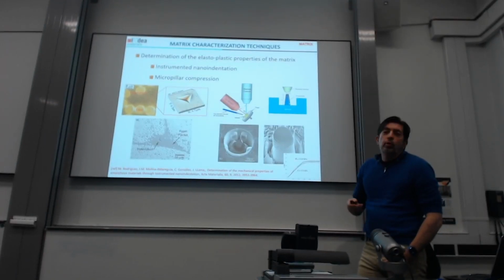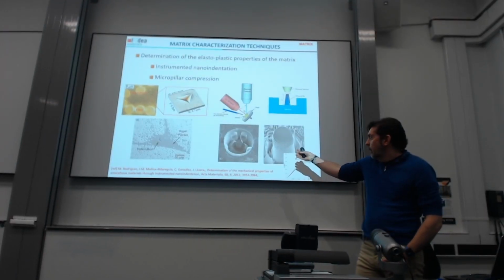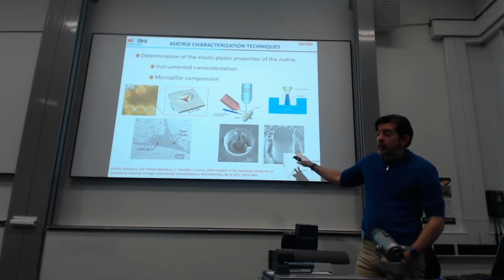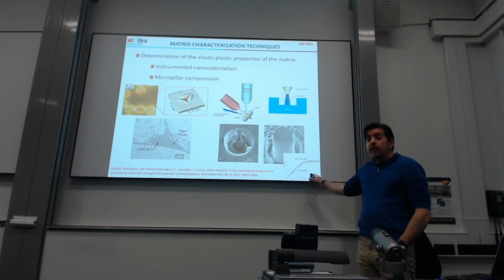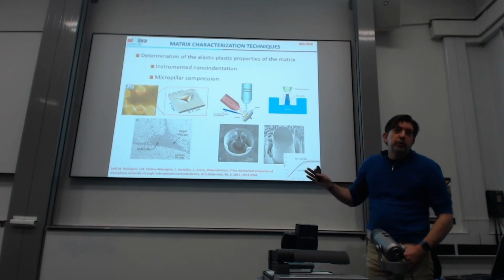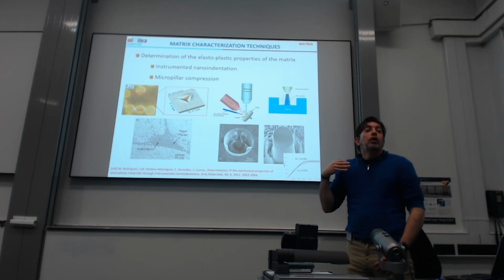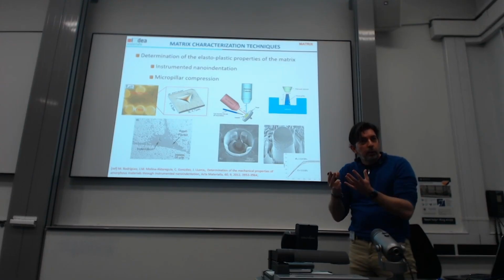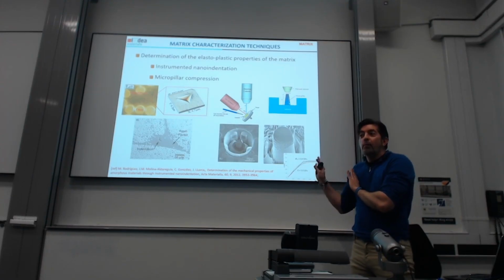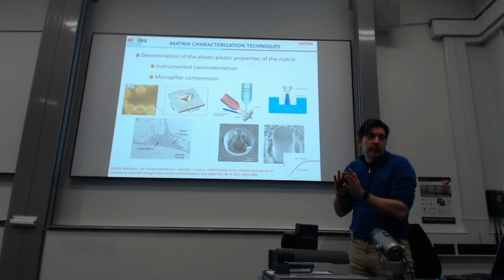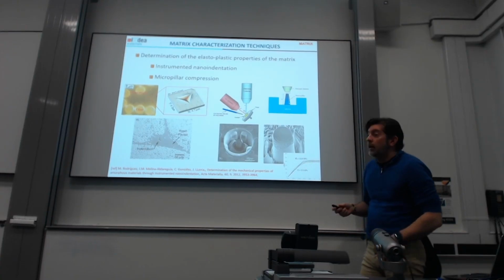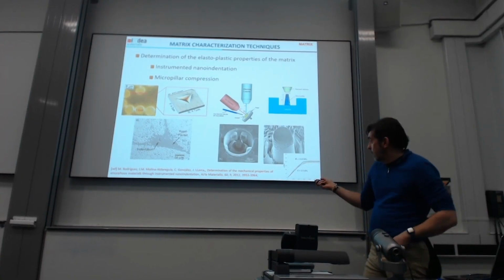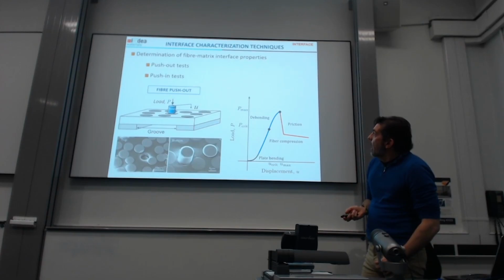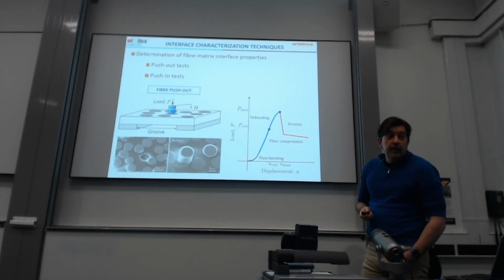Or we can also do micropillar compression. We can create FIB micropillars in the resin pockets and obtain the stress-strain curve directly. The problem with this, of course, is FIB damage: you create a stiff skin around the polymer, so it's not easy. But there are some alternatives to indentation, and you have to use specific techniques for this. We are going to move now to the interface characterization.